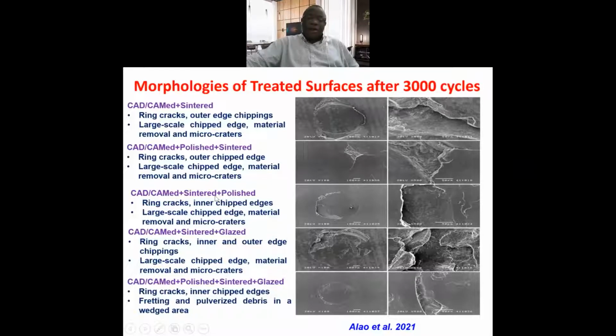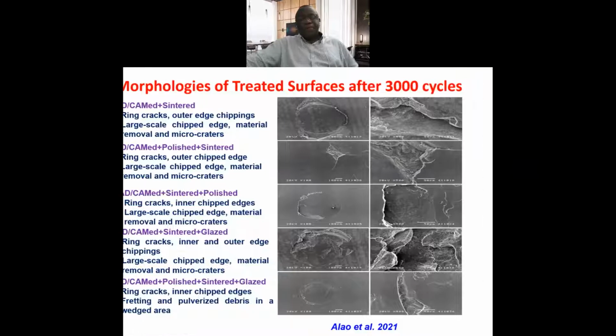Then for the CAD-CAM sinter polish, you can see the ring cracks, inner chipped edge, and the large-scale chipped edge, material removal, and micro craters. Then CAD-CAM sintered glaze, we can see the ring cracks, inner and outer edge chippings, large-scale chipped edge, material removal, and micro craters. Then for the CAD-CAM polished sinter glaze, you can see the ring cracks, inner chipped edges, and then fretting and pulverized debris in a wedged area.